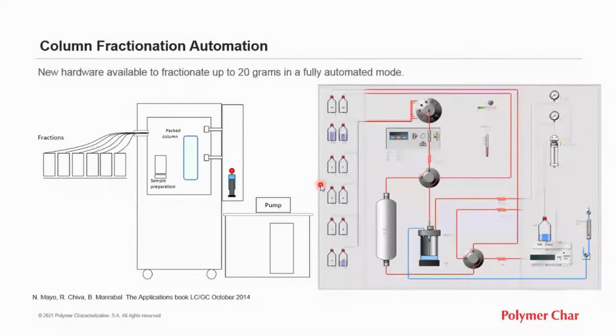of polymer. Here we see a diagram of the instrument with a stainless steel vessel for dissolution, and then a large column for performing the fractionation, and a series of collection bottles outside of the instrument to collect the fractions. There is a pump, which could be a regular isocratic pump for TREF, Crystaf mode, but also a quaternary pump to prepare solvent mixtures when required for molar mass fractionation.